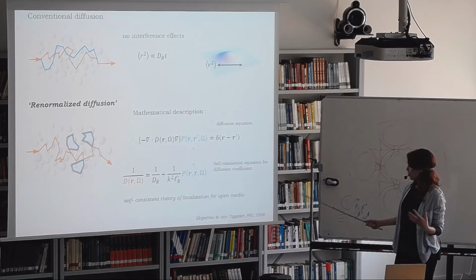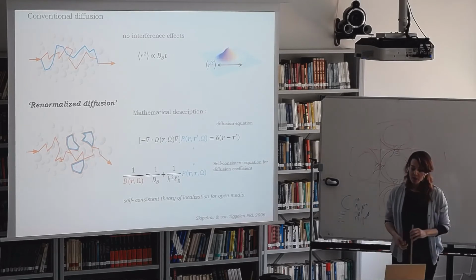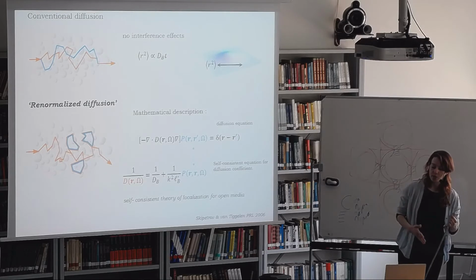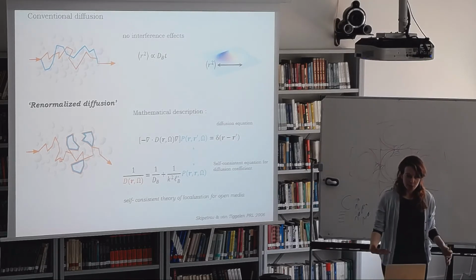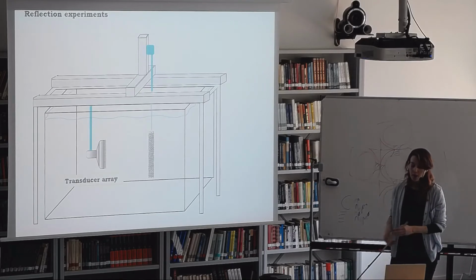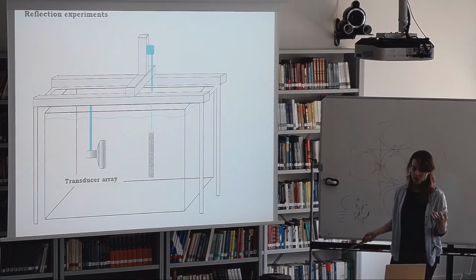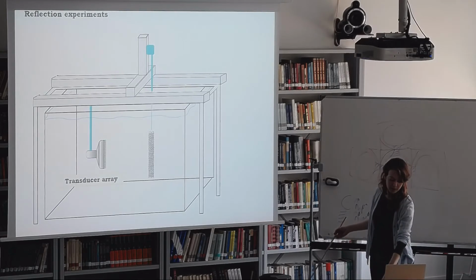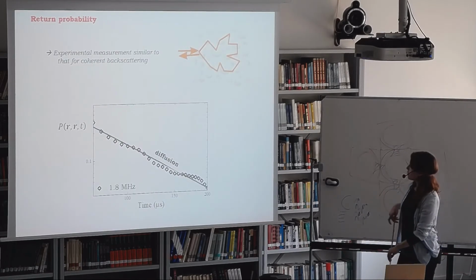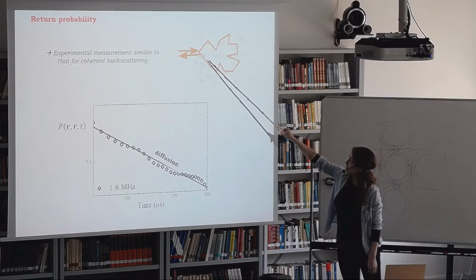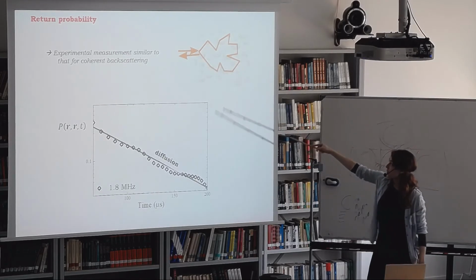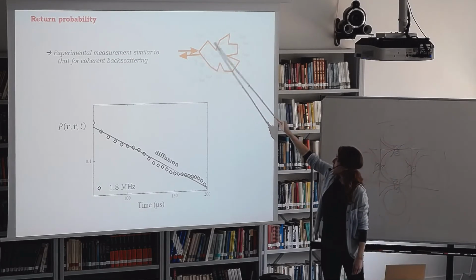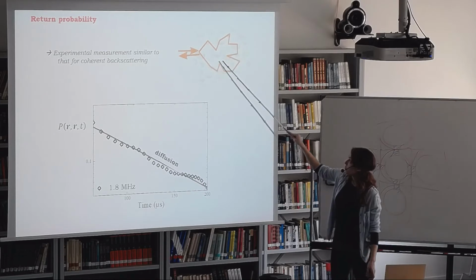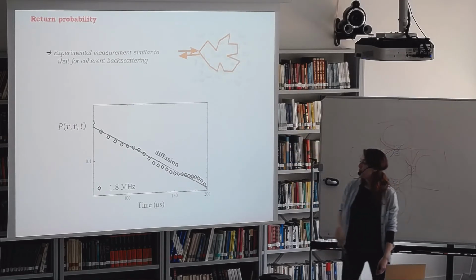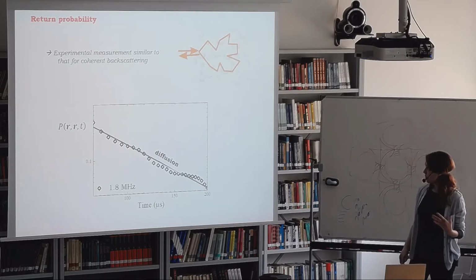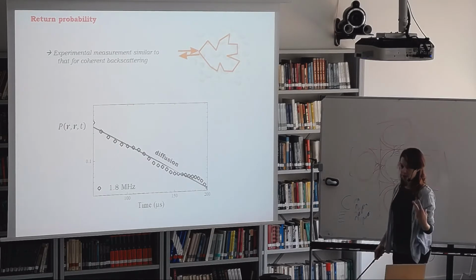So this seems like a reasonable description, very intuitive. And what's really nice is that we have been able to measure somewhat directly the return probability and observe this behavior. The experiments are performed in the same way as with the previous ones in the reflection geometry. But this time we're measuring only the signals that are input and output at the same spot on the sample surface. So we're kind of directly measuring the signals that are input, and they make some kind of multiple scattering path inside the sample, and they come out at the same spot. And so this is a rather direct measurement of the return probability. The waves are returning to somewhere they've previously been.